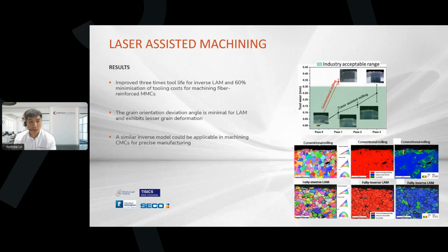As I mentioned before, we have systems and capabilities not only to perform all of these laser-assisted machining capabilities, but our laboratories also have the ability to verify our quality and to consistently prove it. As we can see right here, we're able to monitor our quality down to the metallic grain, in which we can even compare. This is what it looks like, as we can see in our pictures to the right, when we machine a workpiece with only contact-based solutions versus when we use the laser-assisted milling solutions, and we're able to achieve the uniformity that we're targeting, as well as the dimensional quality and the dimensional tolerance that has been set